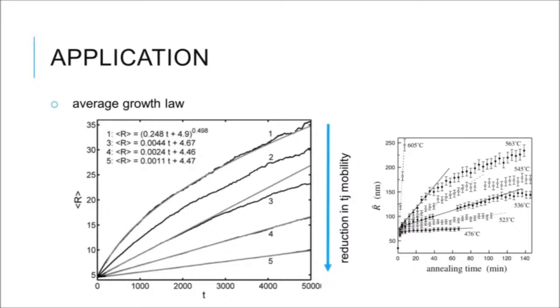Looking more closely, after a short initial period, curve 3 shows a linear relation between average radius and annealing time. However, after quite some simulation time, the simulated curve deviates clearly from the linear least squares fit. This was precisely also seen in the experiment.